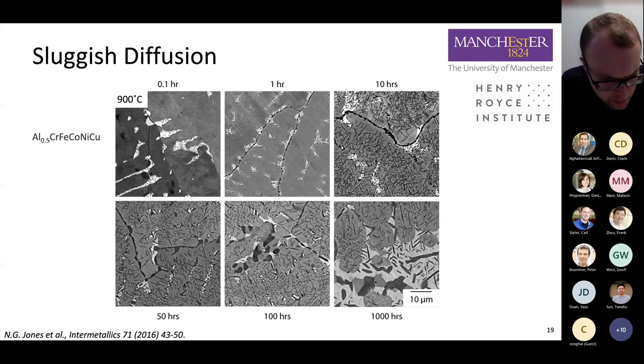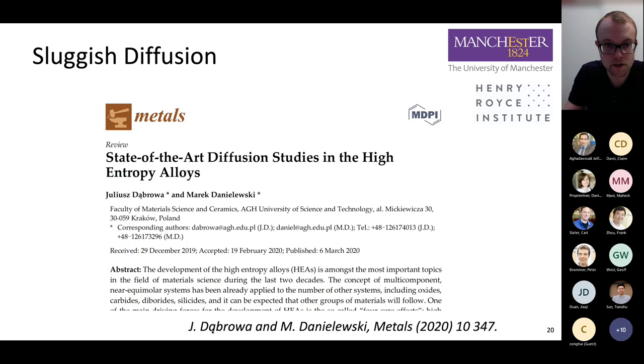Well, if we look at quite a few high entropy alloys and we look at their aging response as an indication of how fast diffusion might be, we actually find that, well, this is within 6 minutes at 900 degrees C, then an hour, and then 10 hours, we see that diffusion isn't ridiculously slow, certainly in comparison to what we see in lots of nickel alloys here in the development of microstructure. And actually, people who've done proper diffusion calculations and diffusion studies,